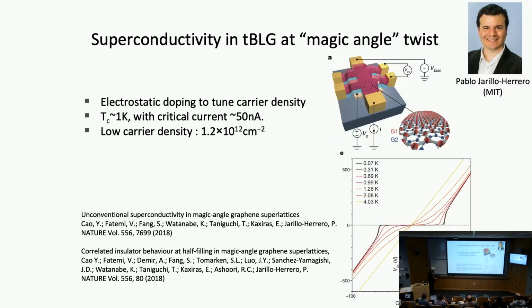And things became even more exciting around 2018 when the group of Pablo Jarillo-Herrero at MIT put two layers of graphene with a slight twist between them and measured the voltage across the sample as a function of the current. And for temperatures below a certain temperature, there's no voltage drop. So basically, this is a superconductor. So the discovery of superconductivity in this system basically changed everything because now you could create a superconductor out of a very cheap material like graphene simply by introducing this twist between successive layers. Graphene or graphite itself is not superconducting.